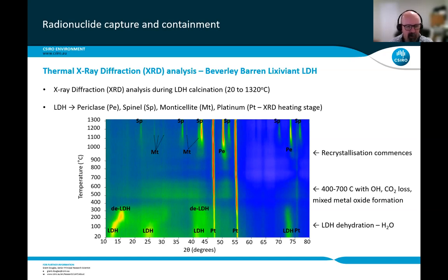Then as you move above about 200 degrees, not a lot happens, but then once you get to about 500, 600, 700 degrees, you can see some faint green patterns on the XRD trace, and those correspond to you starting to form those mixed metal oxide layers as you've lost your water through dehydroxylation and CO2 from your interlayer carbonate bicarbonate. And then again, not a lot happens until you start to get up to about 900 or 1,000 degrees. And so what you then initiated is recrystallization of this layered double hydroxide.